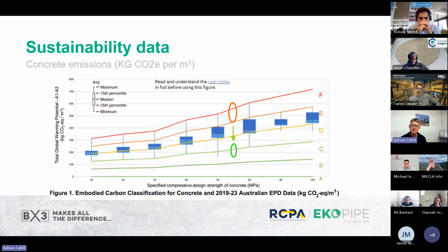Now, I've put this in the sort of 50 to 65 MPa range. We don't actually have a mandate on compressive strength, but that's where our concretes typically lie, in the sort of 55 to 60 range. So this just shows that this is the band that we are in with a standard Portland cement concrete pipe. Quite high. A lot of that's driven by the need to achieve those early strengths, so we do run a relatively high proportion of cement.